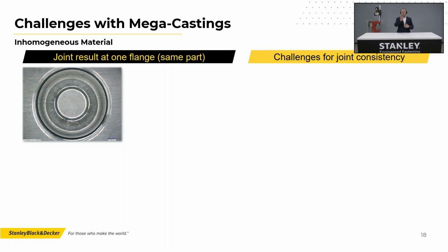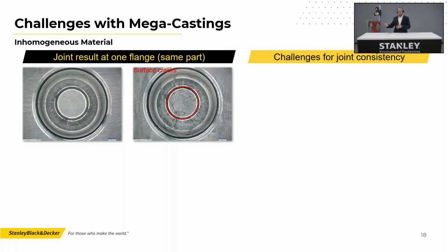So in the past, you can see a nice button there on the page. In the past, we would just select for your material combination the perfect rivet and the perfect die. We would do settings, we would do cross sections, we would check the button, and then we say, okay, that's the rivet and die for this combination, works perfect, your interlock is good, all of that, right? But now the situation changed, because only 2 centimeters to the side on the same part, we see this. So we see, oh, now there are cracks on the surface. They are not really deep, but you can see some cracks on the surface of the cast with the same rivet, the same parameters, and the same die.